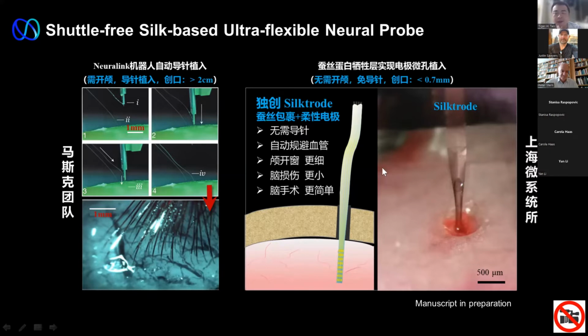So in our case, we try to avoid that. We avoid using any rigid part here. We just use silk as a temporary coating layer. We coat this neuron probe, only 1 micron thick, with silk layers. We tune the mechanical properties of this coated device to be hard enough so that it can be implanted, but soft enough that it won't damage the blood vessel. The main reason they need to open up this window is that they need to see where the blood vessels are so that they can avoid them.